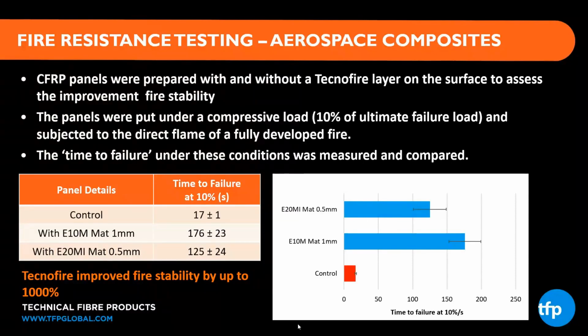A second set of panels was then fabricated, and these panels were put under 10% of this ultimate compressive load to failure, and the panels were subjected to direct flame of a fully developed fire. And this was a really severe thermal event. It was about 175 kilowatts. If you think that cone calorimetry testing, which is quite an extreme test, is undertaken at 50 and 25 kilowatts. So this was really hitting these panels with a fully developed fire. And the time to compressive failure under these conditions was measured and compared.